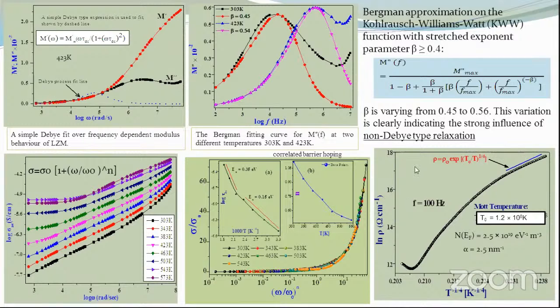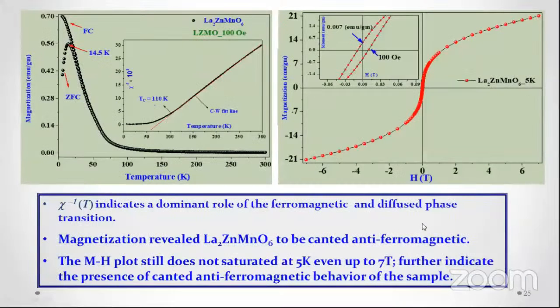Sure. Okay. So these are various models to confirm our modulus data, and this is AC conductivity. The AC conductivity decreases with decrease in temperature, and shows the DC conductivity at lower frequency range. From this DC conductivity, we have again calculated the activation energy. And here, this is the scaling behavior. This shows the dynamic processes at various frequencies as temperature independent. And this is the resistivity of this material using Mott formula.